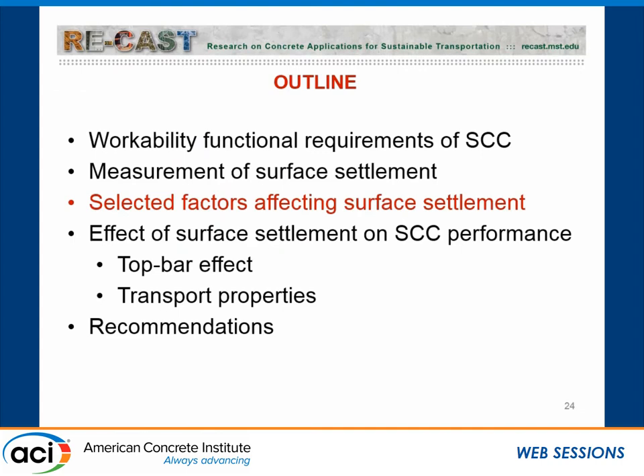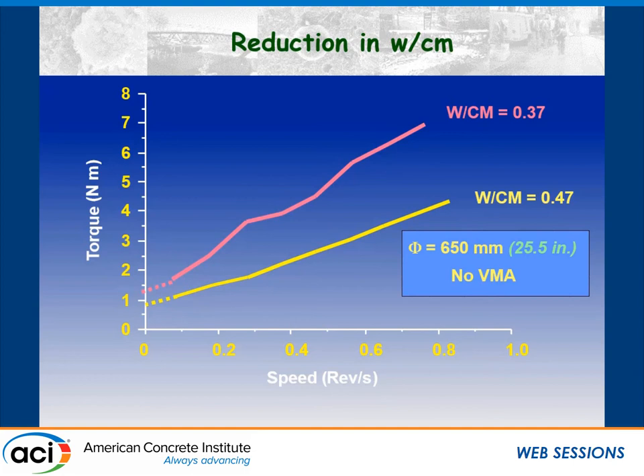So what are some of the factors? Well, one of the factors affecting stability is the water-cement ratio, because it's affecting rheology. Here you have rheograms between the torque and the rotation velocity of the rheometer. You have two SCCs with the same slump flow. None of them has any viscosity enhancing agents, but the water cement ratio is different. The pink one has a lower water cement ratio. It's more viscous. It has more superplasticizer to adjust for both of them to have the same initial shear stress, which is the yield stress, slump flow. But this one is more viscous, and the viscosity is giving you higher stability.